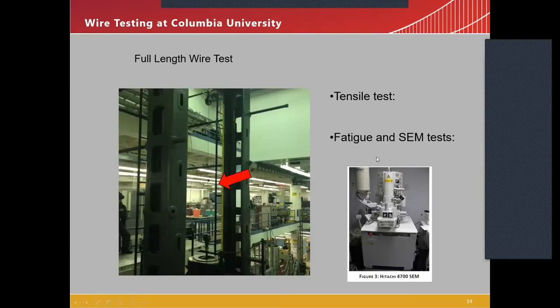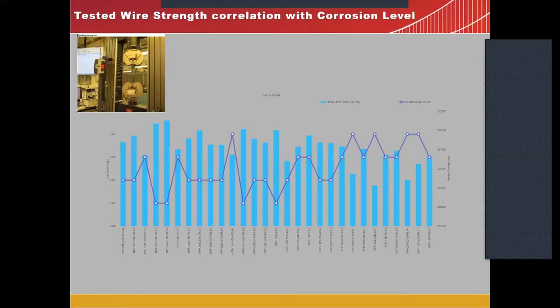Wire testing. Wire testing was done at Columbia University. It was full length wire test, tensile test, fatigue and SEM tests. Tested wire strength over here shows the tested wire strength correlation with the corrosion level. Of course, the worst portion has the lowest strength.